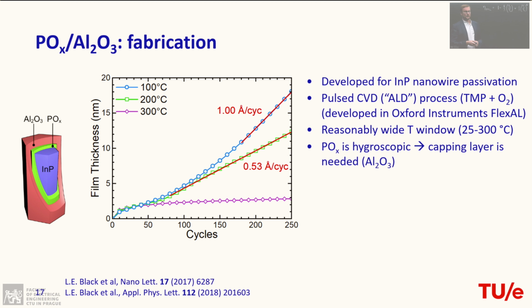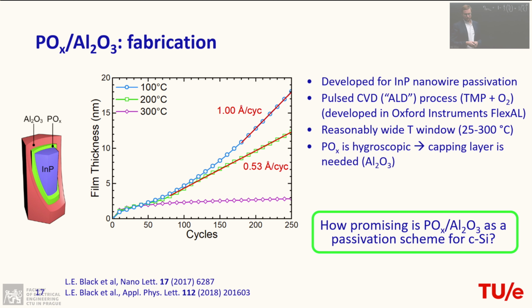It was also established that phosphorus oxide is really hygroscopic, so if you don't cap it with another material, it reacts in air immediately after you take it out from your deposition tool, and that's not what you want. So the capping layer chosen was aluminum oxide, just because it's very easy to make it with ALD, and it is a known process. So this stack was born like this. And then the question was, is it possible to actually passivate crystalline silicon with this stack?